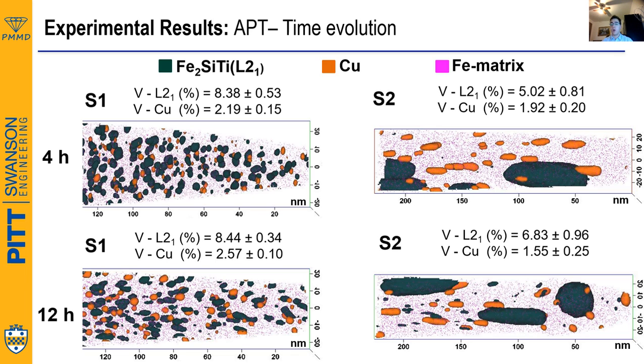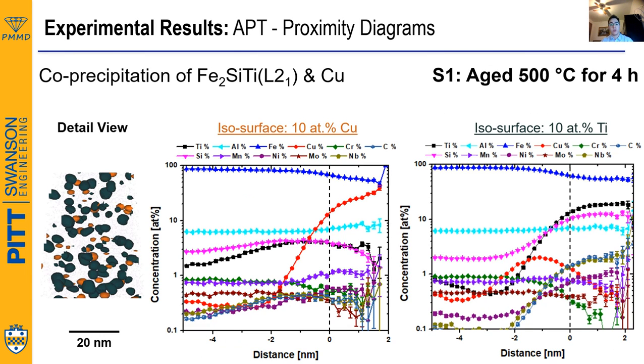Finally, a detailed look at these APT images and the use of proximity diagrams allows us to not only identify the composition of these precipitates, but also to confirm that co-precipitation interaction occurs between the copper and the L21 precipitates. Here, for the case of S1 aged at 4 hours, we see on the figure to the left that the silicon and titanium content increases in the proximity of the interface between the ferrite and the copper precipitate. This same behavior is portrayed in the case of copper content increasing in the vicinity of the interface between the L21 and the ferrite phase.